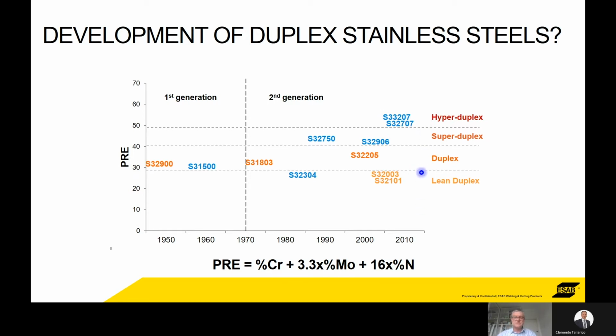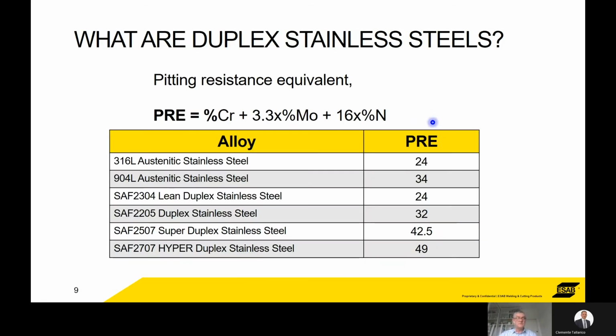So in terms of tensile strength, we've got a big jump from lean to duplex to super duplex, and then from super duplex up to hyperduplex. Okay, and I'll show you that later on. So looking at this PRE number, this magic pitting resistance equivalent number, in terms of, say, a standard stainless steel, a 316L stainless steel has a PRE of 24.